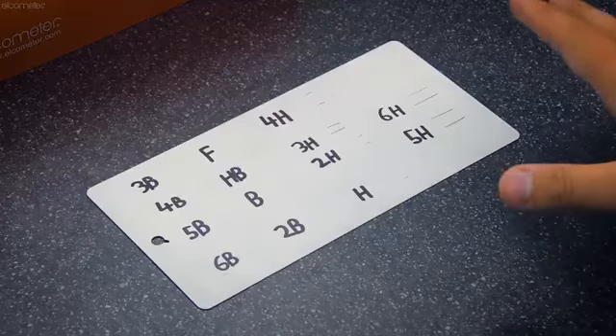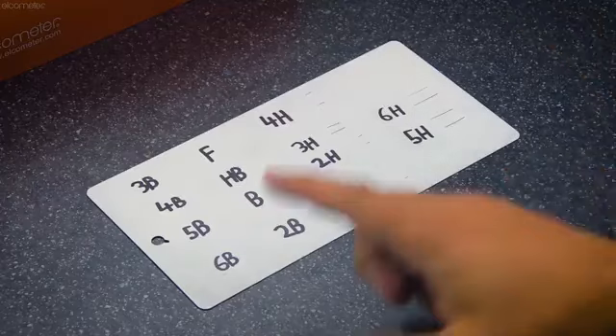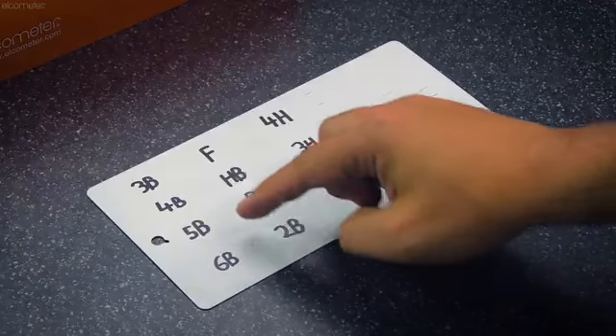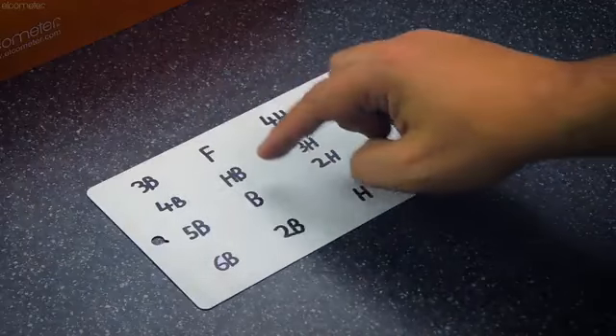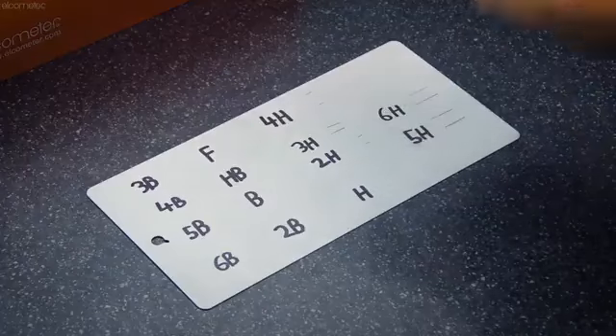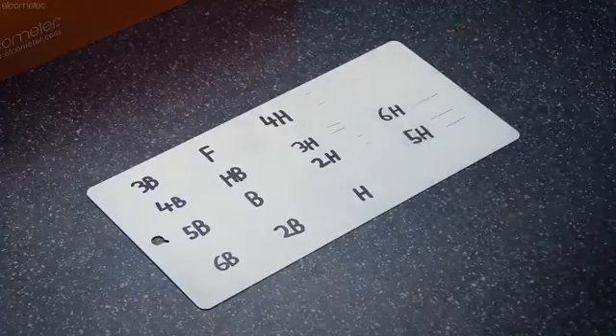So let's go back to our test panel. If we were to start at the softest pencil and work up, the softest pencil to leave a mark of over 3mm long is 2H. Examining the results a little closer, you can see that the majority of the mark is a cohesive fracture, so it's cut through the film. And on the edges of the results, you can also spot a little bit of plastic deformation.